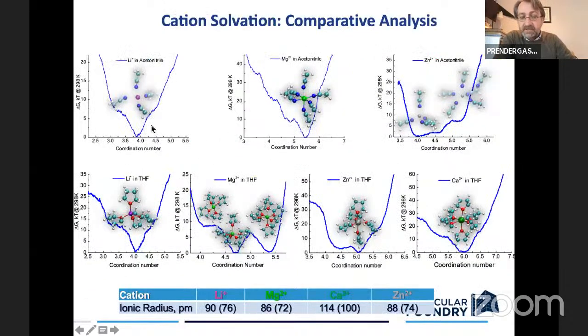Okay, magnesium isn't unique in this sense. We've looked at other species. Some, like lithium and acetonitrile or calcium and THF, are dominated by a single free energy minimum. So you have truly one solvated species. But many others have multiple free energy minima with respect to coordination number, and sometimes even plateaus, meaning that there's a fluid exchange between different coordinations that exists in solution. You can think about this being related to the charges of the molecules and their actual sizes as well, and somehow how easily the solvent molecules can pack around these different species could define their overall free energy landscape.